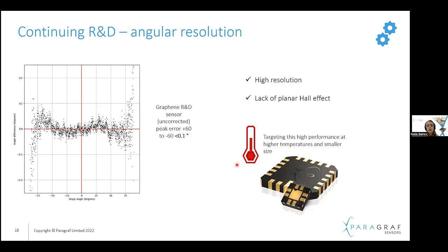So joining onto that a little bit with the angular resolution results. Again, this is something that is performing really well at ambient temperatures. This plot here just shows an example test of an R&D sensor using angle measurements over roughly 60 degrees to minus 60 degrees. And we can see that the peak error within that range is less than 0.1 of a degree. So this is a really promising result for a bare device, if you like, because it's quite competitive with conventional sensors once they've had corrections and post-processing to the data.